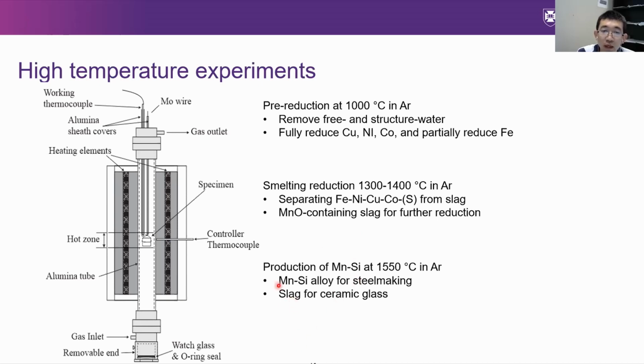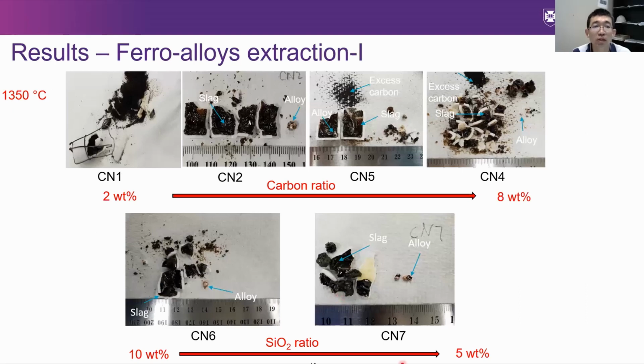At an even higher temperature, like 1550 degrees, manganese silicon alloys are produced. This alloy is normally used for steel making, and then the slag can be used for ceramic glass. So this is ideally a zero waste of fully using the nodule components. This is the result where we extract the critical metals to produce ferro alloys at 1350 degrees,